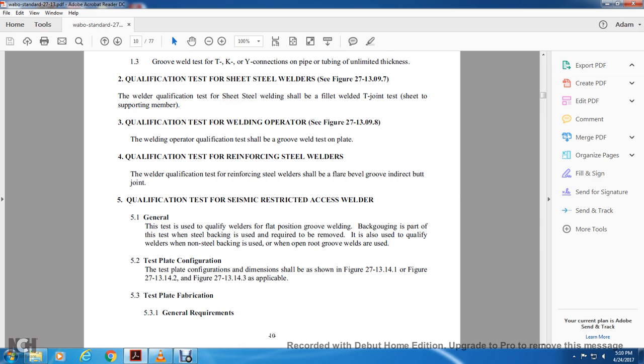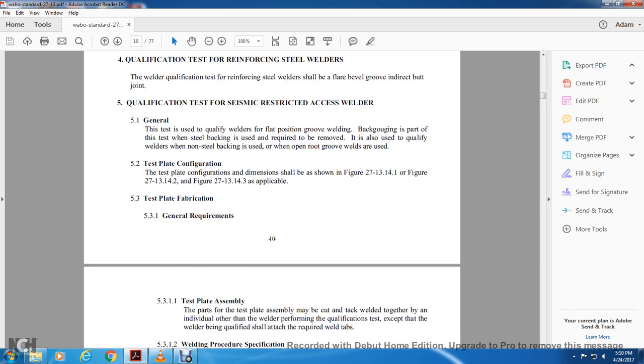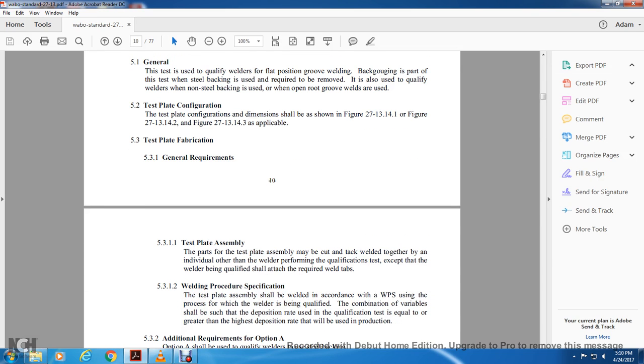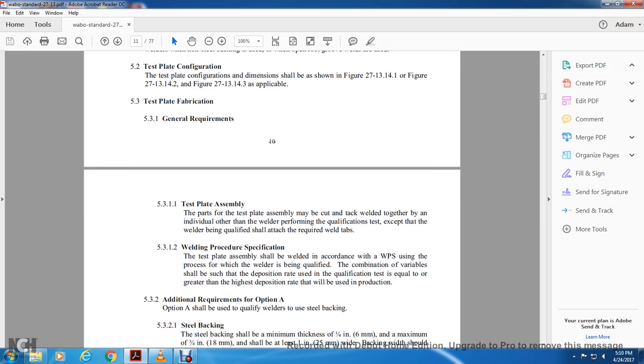5.3 Test plate fabrication general requirements. Test plate assembly. The parts of the test plate assembly may be cut and tack welded together. Any individual other than the welder performing the qualification test, except that the welder being qualified shall attach the required welding tabs. Welding procedure specification. The test plate assembly shall be welded in accordance with the WPS using the process the welder is being qualified for. Combination variables shall be such that the deposition rate for the qualification test is equal to or greater than the highest deposition rate that will be used for production.